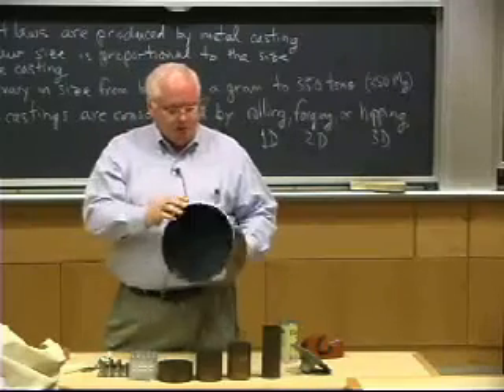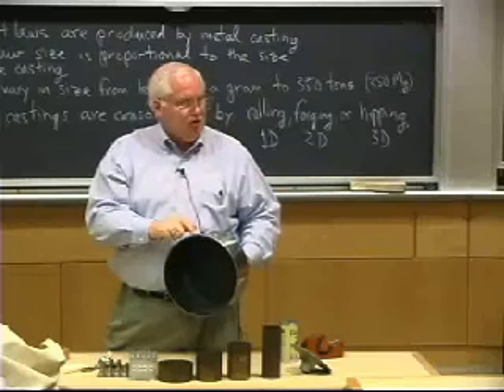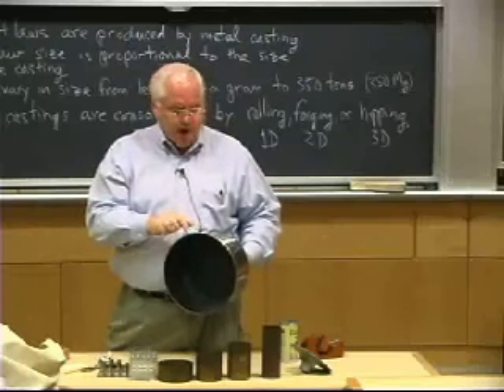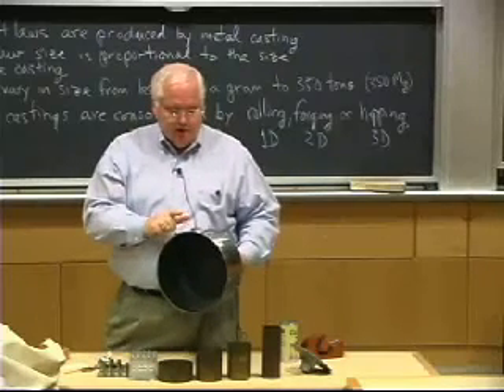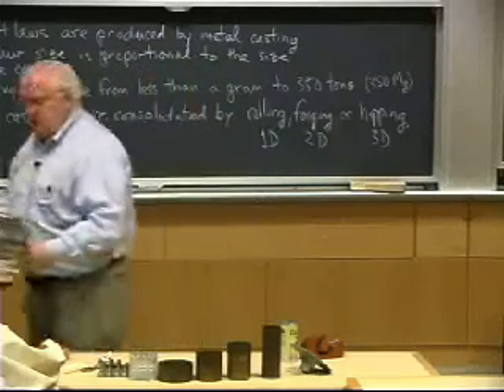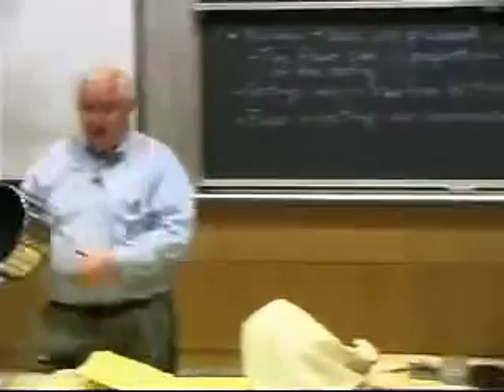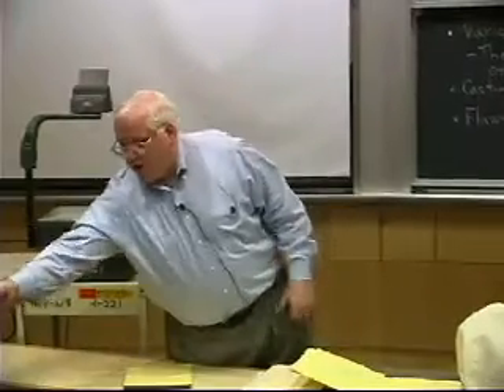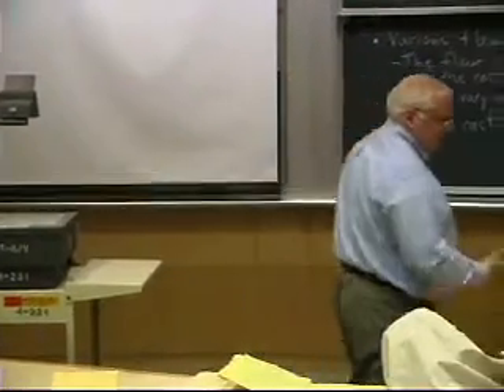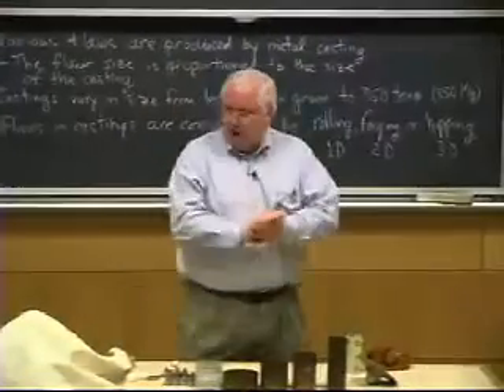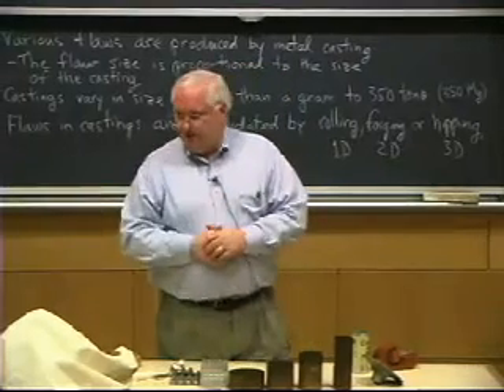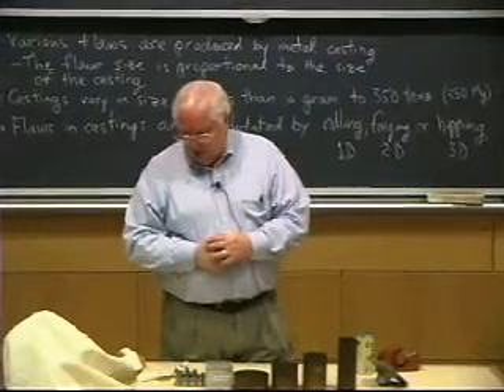No cracks, ship it. On the way across the ocean, it has time for the hydrogen cracks to show up where you have the maximum amount of the martensitic crystal structure of the steel. You also have residual stresses up here. You have to have stresses to get the hydrogen cracking. So that's the story of residual stresses, transformation, hydrogen cracking, all coming together to give you a defect in your product.